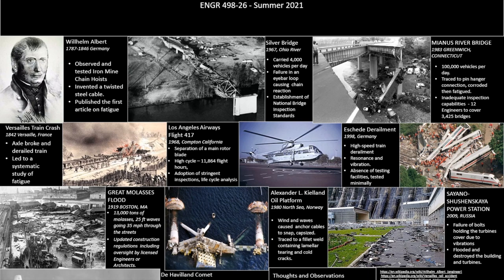Below that, Los Angeles Airways Flight 417 crashed in 1968 in Compton, California. The main rotor separated, resulting in loss of control, which killed all on board. Fatigue due to high cycles, 11,864 flight hours, and a combination of improper shot peening, poor metal hardness, and pitting was the cause of fatigue failure. Investigations by the NTSB resulted in the adoption of more stringent inspections and life cycle analysis of rotor parts.